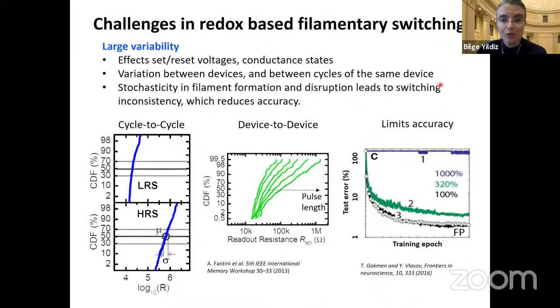Okay. So the challenges with these devices that change their resistance by oxygen vacancy filament formation is the large variability or lack of repeatability. And by that, what I mean is large changes in the conductance states that you obtain with the same voltage, or changes in the set reset voltages that vary from device to device, such as seen here for readout resistance that varies more than an order of magnitude for the same material, but different fabricated devices or different elements. It should in theory be the same, but they're not the same intrinsically.